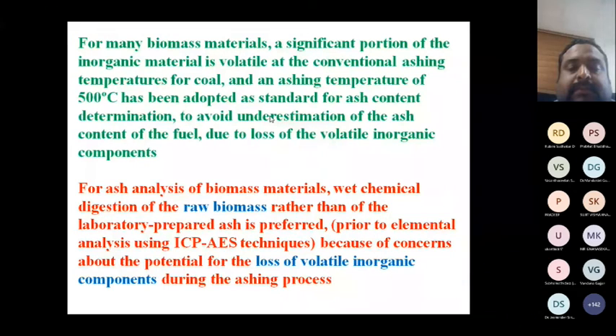Similarly, for ash analysis, for the iron oxide, silica and other components in the ash, for biomass material normally wet chemical digestion of the raw biomass is used rather than the ash. If you want to determine the ash composition, silica, alumina, iron oxide, calcium, magnesium, you do not take the ash, because some of the ash may go off as volatile. So the real composition you cannot get. That is why raw biomass is preferred over laboratory-prepared ash, because of concerns about the potential loss of